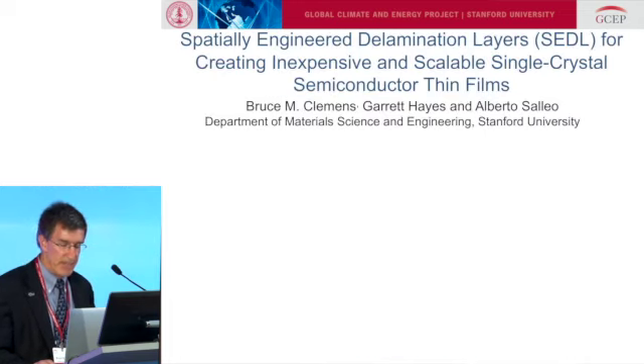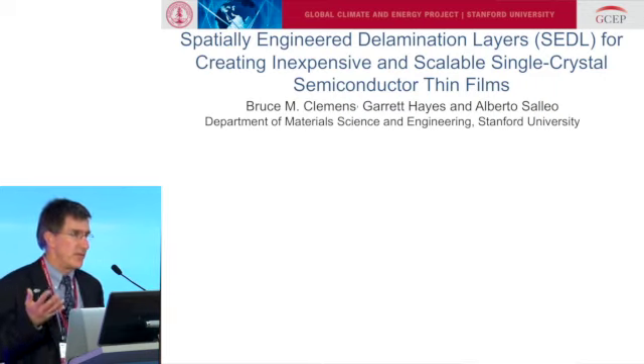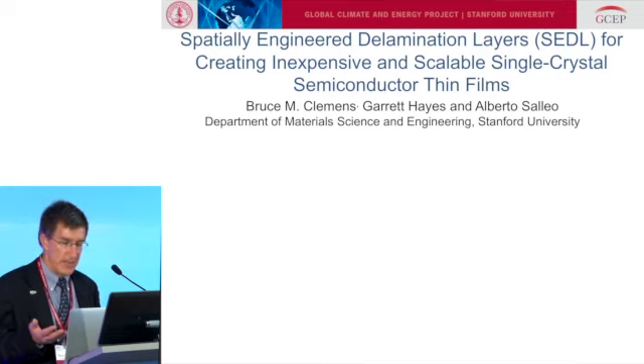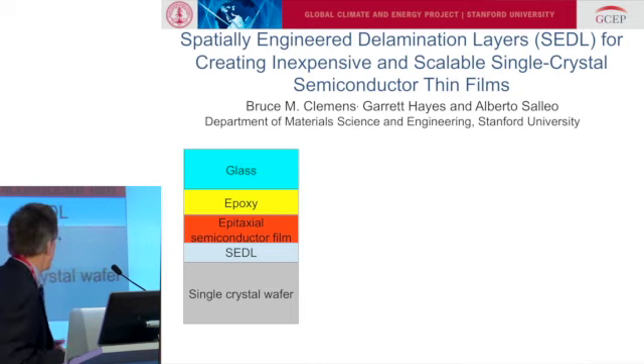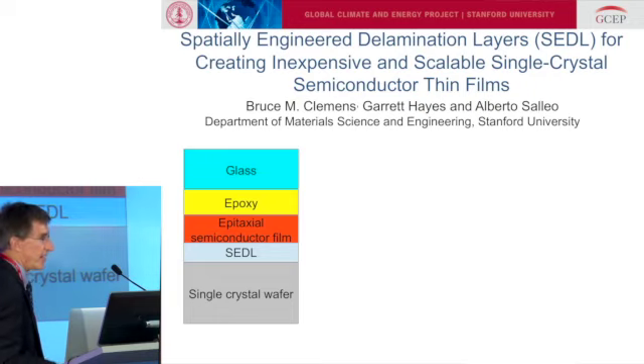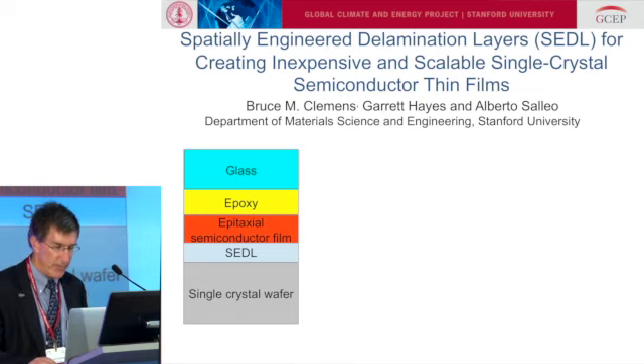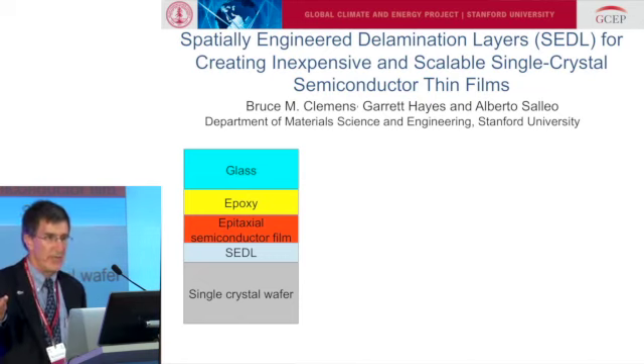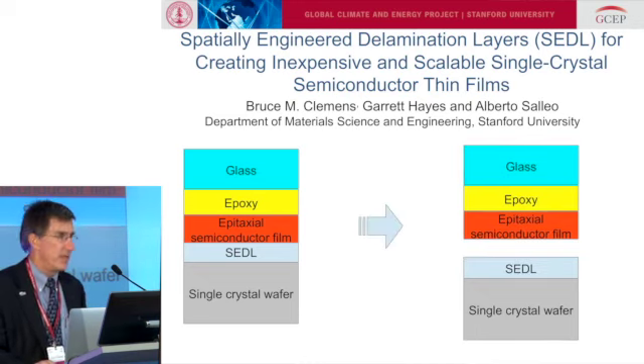The last thing I'll talk about in terms of our work is a technique for making single crystal materials with a thin film process that doesn't consume a single crystal substrate. And this is a spatially engineered delamination layer. What we do is we grow with epitaxial growth on a single crystal substrate, but we first put a mechanically weak layer, and then we grow the epitaxial semiconductor on top of that. And then we can bond glass to it, peel it off, and then we have this thin film, high quality material on a cheap substrate.